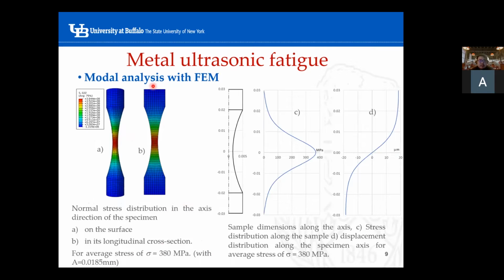So this is a modal analysis with finite element simulation results. We can find the average stress amplitude around the gauge center. This one is on the surface, this one is the cross-section view. And this one shows the average stress of around 380 megapascal with an applied displacement amplitude of about 0.018 millimeters.